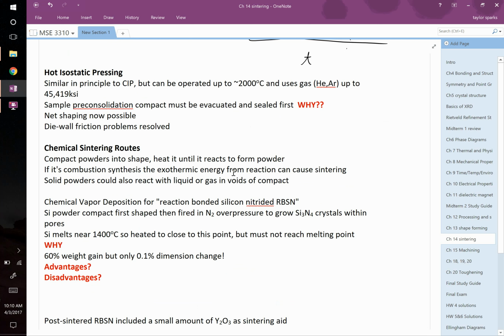Hot isostatic pressing is pretty rad. You can do it up to about 2,000 degrees Celsius. So no water is going to survive that, so you're clearly not using water. Instead of using water as the pressure medium, you're using a gas. So you put it in a box, an empty box, you pump this thing full of some gas, and then you apply pressure to that gas itself.